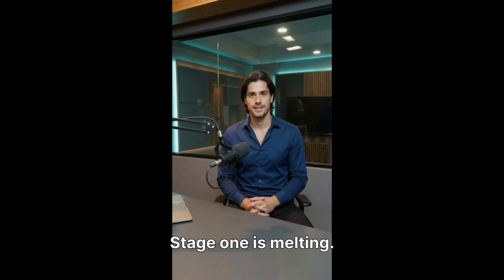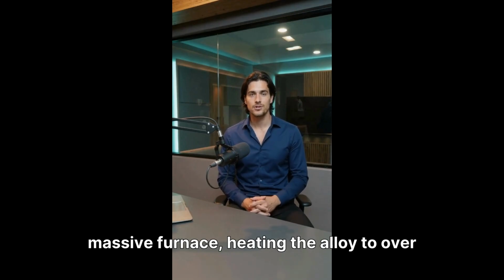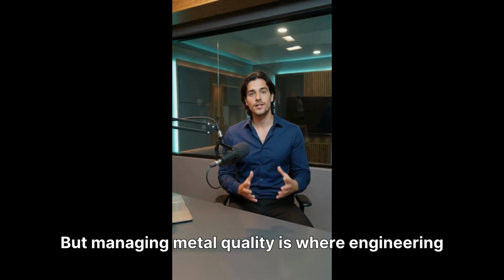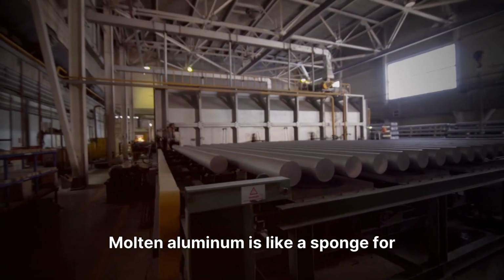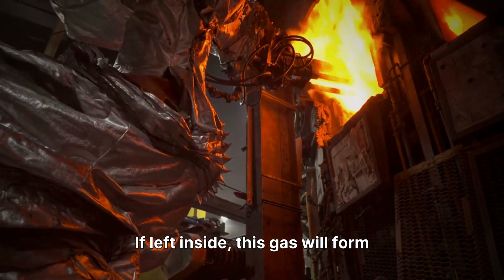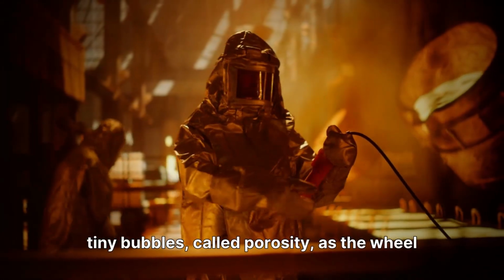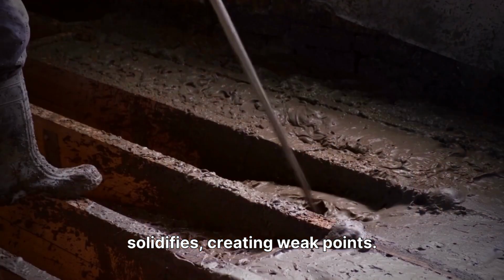Stage 1 is melting. The raw billets are fed into a massive furnace, heating the alloy to over 700 degrees Celsius. But managing metal quality is where engineering is critical. Molten aluminum is like a sponge for hydrogen. If left inside, this gas will form tiny bubbles, called porosity, as the wheel solidifies, creating weak points.